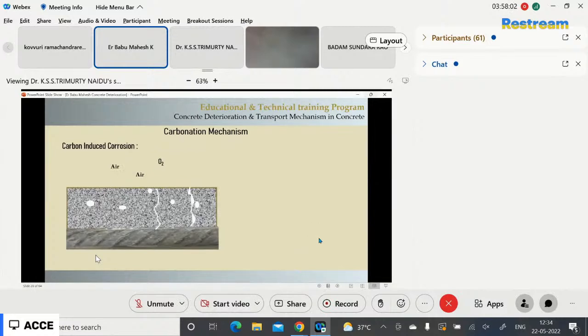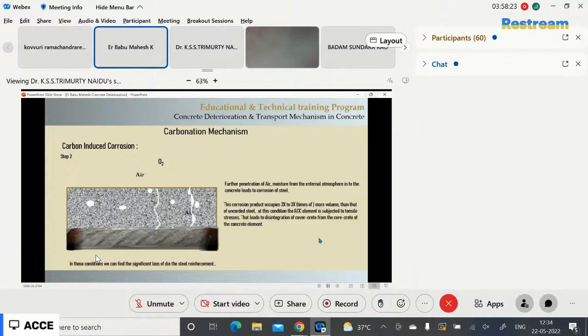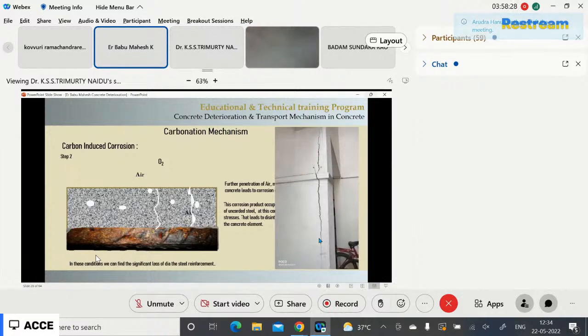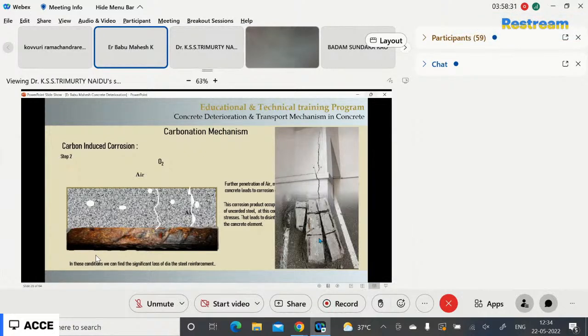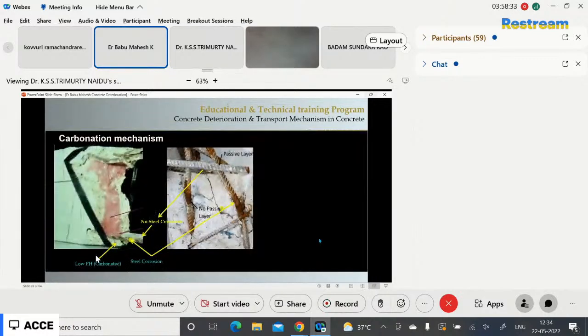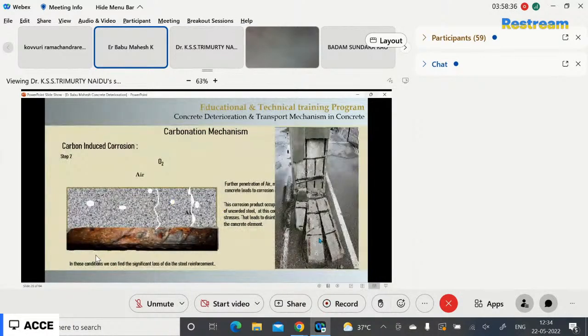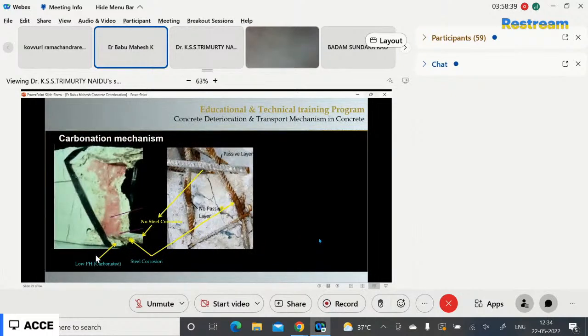During this process, the calcium hydroxide leaves some pores in the paste system. These pores from the carbon dioxide increase the permeability of the concrete as well as decrease the pH value of the concrete. So, in this system, further penetration of air and oxygen from the atmosphere into the concrete creates more problems for the reinforcement. It leads to some cracks in the column and spalling of the cover of the column.